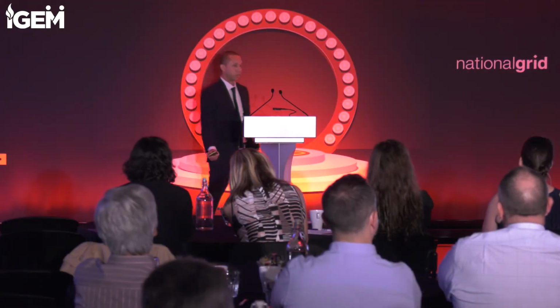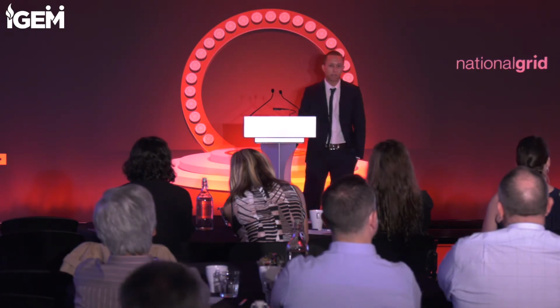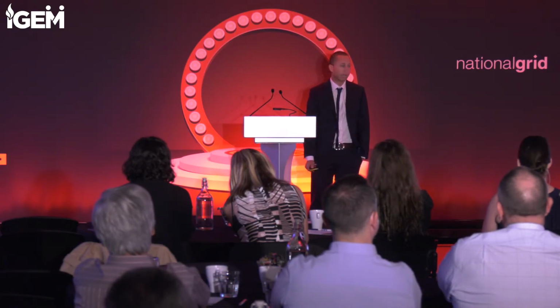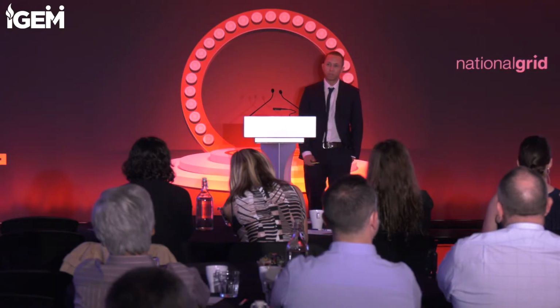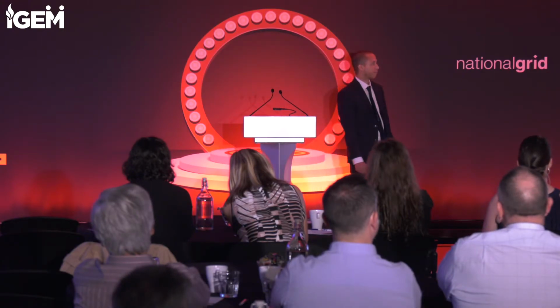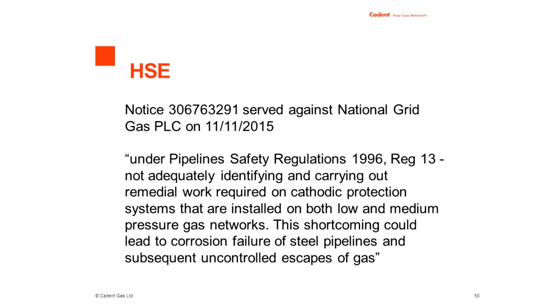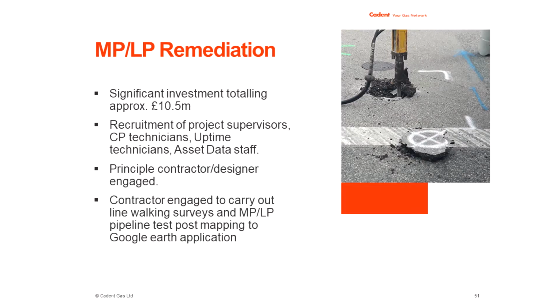So at every test post, our technicians can go along and disconnect the cables, take a reading, and if it's more negative than 850 millivolts, we're protecting our pipelines adequately. So this is where the HSE are interested. Back in 2015, National Grid, as we were then, was served an improvement notice for not adequately protecting their pipelines. And this improvement notice has obviously followed through as we've become Cadent and split off. So that's where the medium and low pressure remediation project originated from.